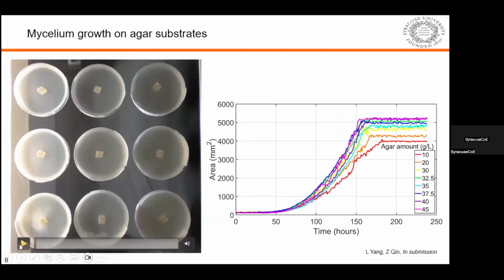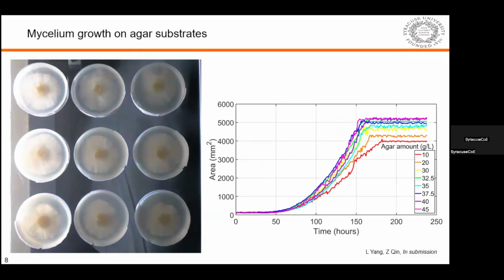So this is a time-lapse video showing that once we have an initial block of mycelium, it can quickly occupy the entire petri dish within a week or 10 days. Here is the curve tracked from this movie, showing how the occupied area increased as a function of time. You can see what happens once you change the composition of the substrate. Here we use agar because it's food grade, very simple to handle, and also bio-safe. Once we increase the concentration of the agar, we effectively increase the stiffness of the substrate. And you see the growing speed also increases together with that stiffness.